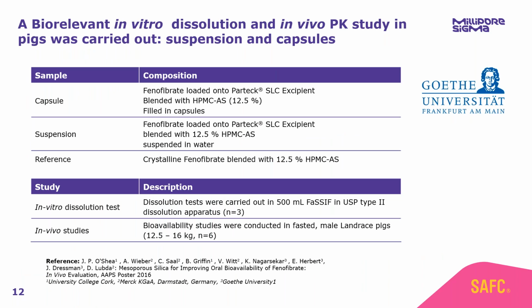In order to assess that, we carried out an in vitro biorelevant dissolution and an in vivo pharmacokinetic study in pigs. We had two different formulations for the mesoporous silica. We had a capsule, so it was simply filled into a capsule, along with HPMCAS, which was a precipitation inhibitor. In addition, we had a suspension, which is typically used in preclinical trials, and we combined our fenofibrate-loaded silica with the polymer in a suspension. We then compared both of these dosage forms to crystalline fenofibrate, so unmodified fenofibrate, that was also blended with the same polymer to rule out any co-solvency effects.